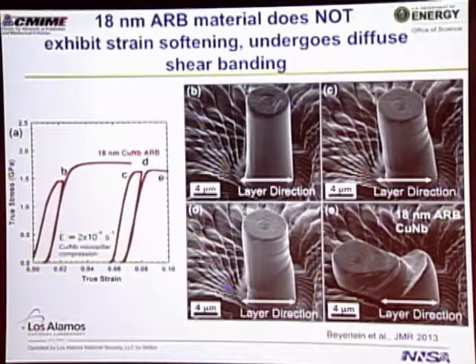Now in this case, we see very, very different behavior. If we load it, take a picture B, and then unload it, load it, we take a picture C, unload it, load it again, take a picture D, and then by the end of the test it looks like this. What you find is that we didn't get that stable shear band anymore. The material didn't soften as we deformed it. And the question is, well, why not? We can section that material too, and sure enough, the layers have broken up. They didn't form this stable kind of deck of cards that could just slide.